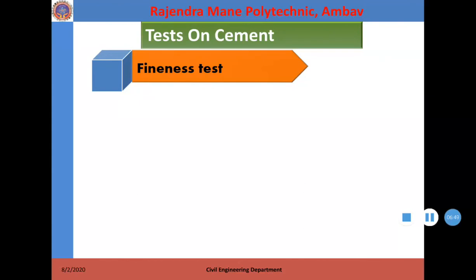The particle size fractions have a major influence on 28th day's strength. An increase in fineness of cement is also found to increase the drying shrinkage of concrete. For commercial cement, it is suggested that there should be about 25 to 30% of particles less than 7 micron size.